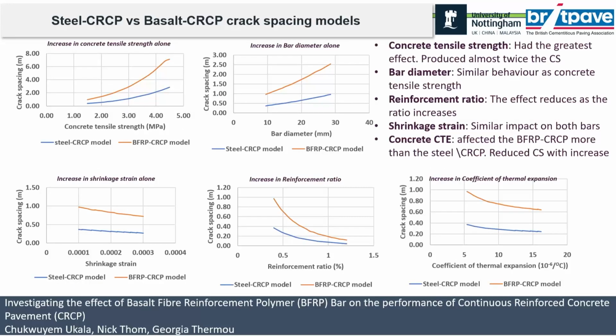And we compared the two results, that of steel and that of basalt bar. What we saw, if you see the red one is the basalt and the blue is the steel, is that if everything is kept constant, we expect double the crack spacing if we're using basalt bar. So if we're using steel and we have a crack spacing of 1 meter, we should be expecting about 2 meters of crack spacing.